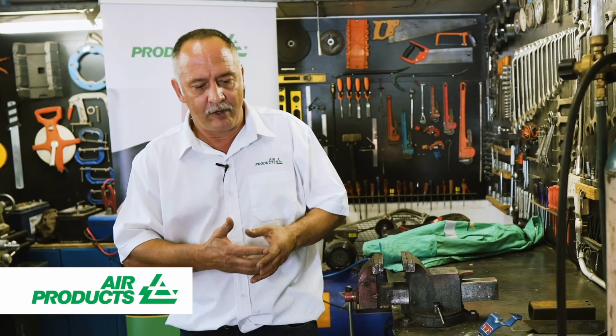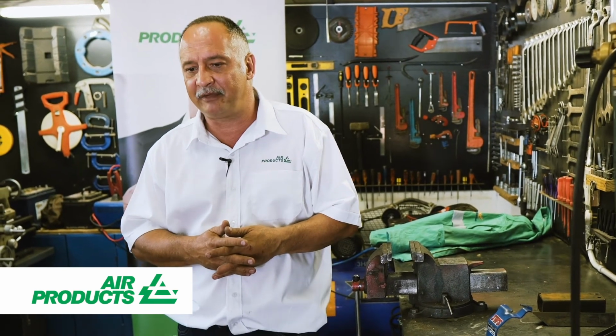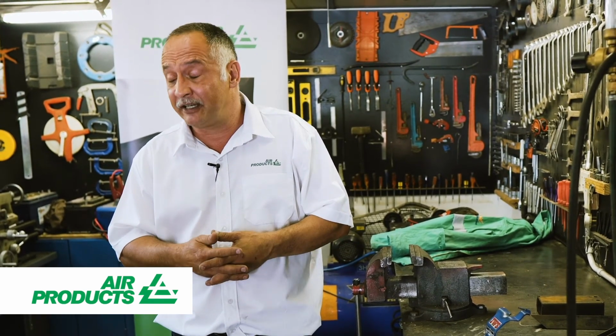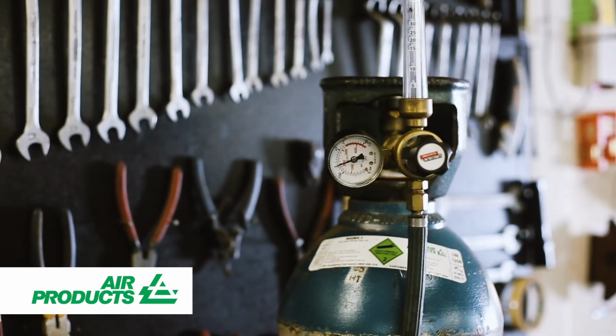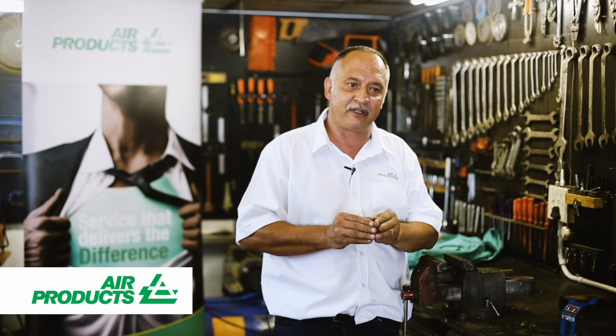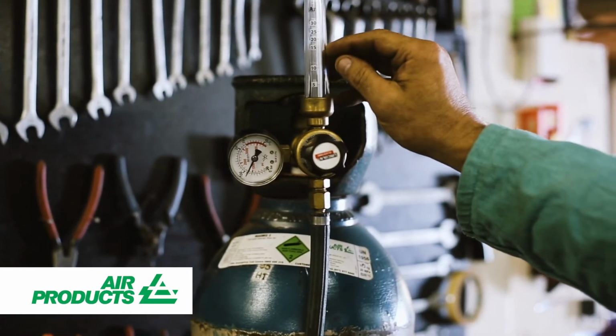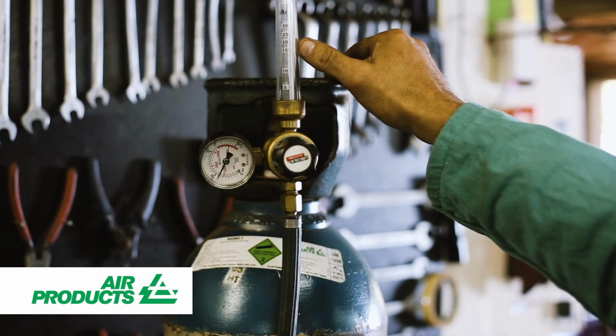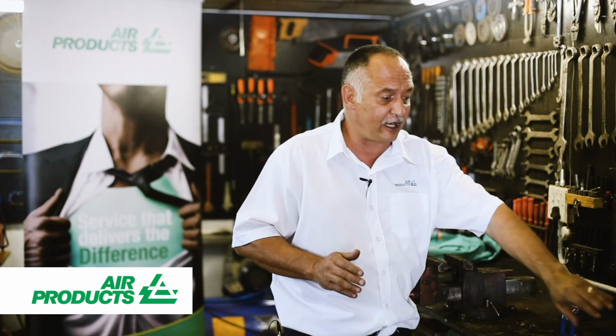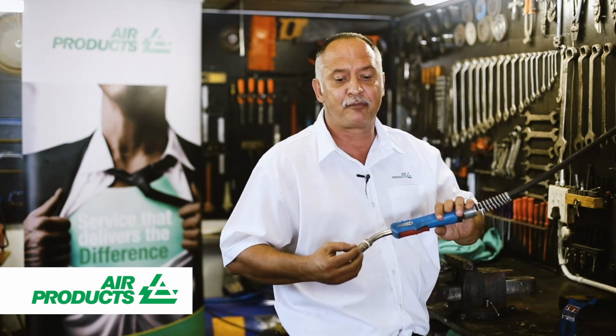However, if we look at the MIG-MAG process, it's prone to have porosity. Porosity in the weld means that there's a lack of shielding, number one, or there's too much shielding. That's why we have a flow meter. A flow meter indicates the required flow that you need to protect the weldment from atmospheric contamination, the air that we breathe. We want to keep that out of the weld. We will set on a MIG-MAG process the flow to approximately 15 liters per minute. This will give us a laminar flow of shielding, exerting the shroud on the welding torch to protect the weld